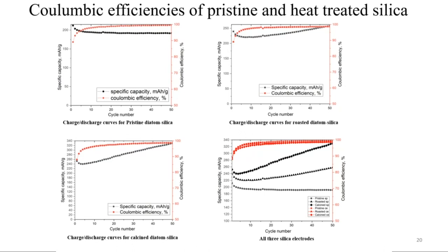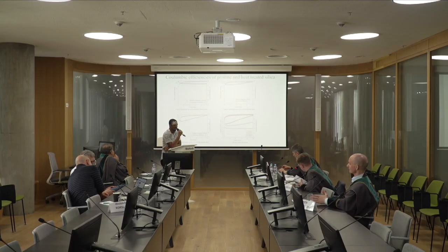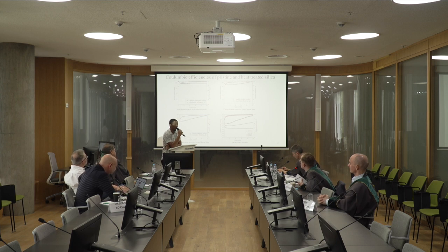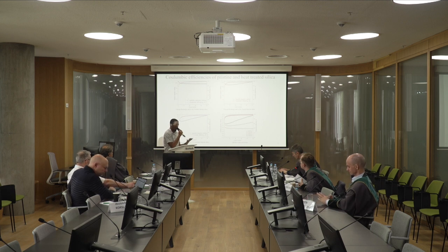Okay. So then why do the calcined samples show the highest capacity compared to pristine and roasted? I think, from our initial analysis and discussions, it's likely due to the different powder characteristics amongst the three silica anodes we used. The calcined powder shows somewhat better powder characteristics, and also I thought about it because the reaction between silica and lithium leads to lithium oxide and lithium silicates and silicon, which is very key, electroactive silicon, which is very key for increasing the capacity.